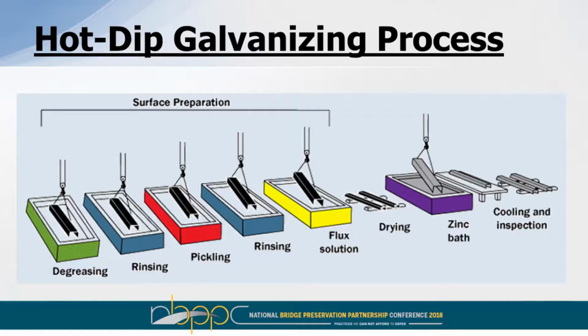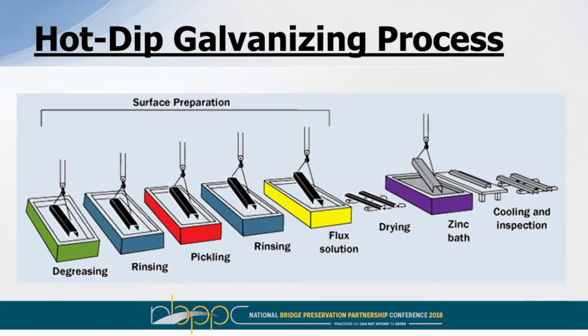We then rinse the acids off again, and then it goes into a flux solution. This prepares the steel to go into the kettle to accept the zinc. So after it comes out of the flux solution, it does need to be dry. It's like when you go to McDonald's and you watch them throw frozen French fries into the hot grease. It spits, it spatters, it goes crazy. You don't want to be around that. So we let it dry before it heads into the bath.